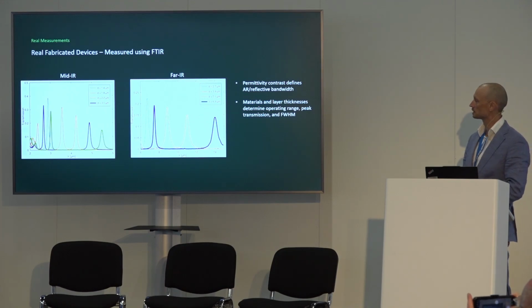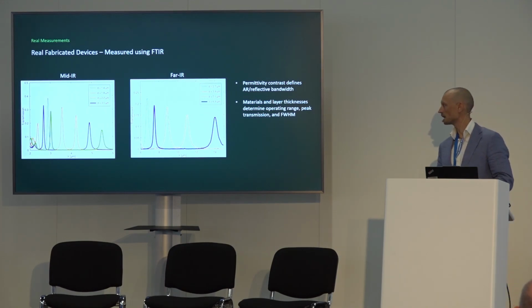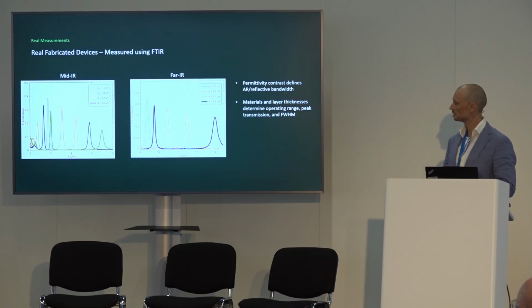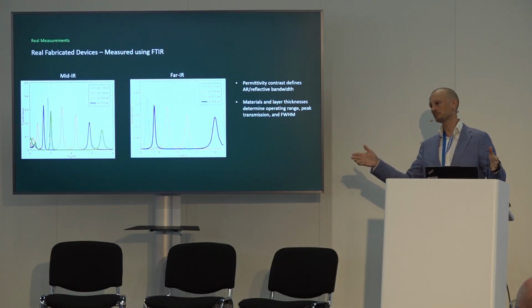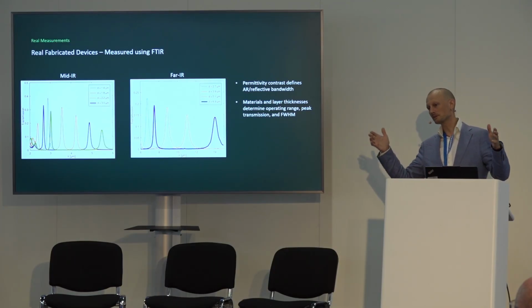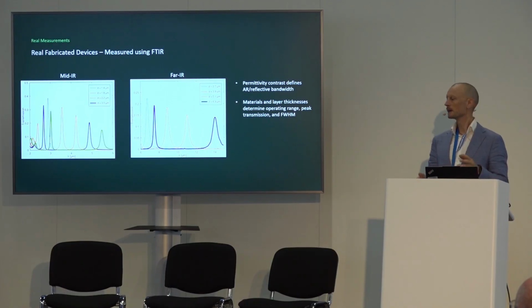Now, continuing to what this looks like in real life, you have measurements here using FTIR, showing that we can scan our filters from 2 to 6 and 6 to 14.5 microns. So we work in the range from 1 to 15 microns. We can't cover the entire range with one filter, but by tuning the materials in our coatings and the thicknesses in our coatings, we can basically tailor our filters to our customers' needs.